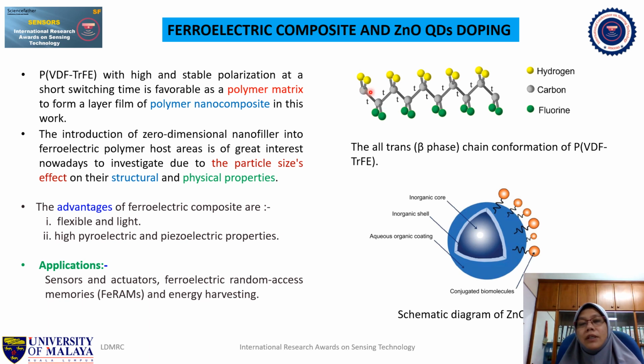In VDF-TrFE, there are hydrogen atoms on one side of the polymer axis and fluorine atoms on the other side of the polymer axis, which is in the trans arrangement. So with this kind of structure, PVDF-TrFE has high and stable polarization with short switching time. These properties would be favorable to use as a polymer matrix to form a layer film of polymer nanocomposite.